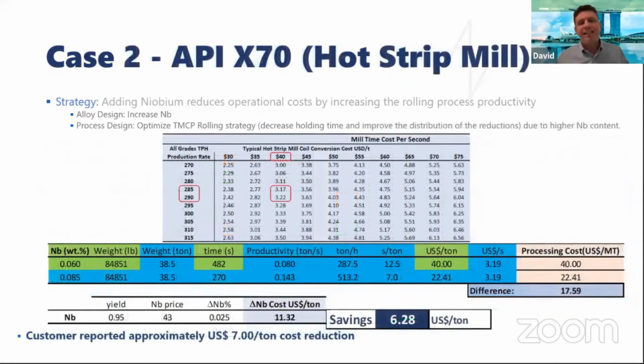This is an API X70 produced in a hot strip mill. Of course, the productivity is much higher in a hot strip mill, and it was produced with 0.06% of niobium and with the productivity of 287.5 tons per hour. The increase of niobium to 0.085 could manage to roll it faster, reduce or eliminate the holding time between passes, and optimize the roughing passes to lower amount of passes and the distribution of the reductions in a way that you could manage to increase your productivity to 513.2 tons per hour,